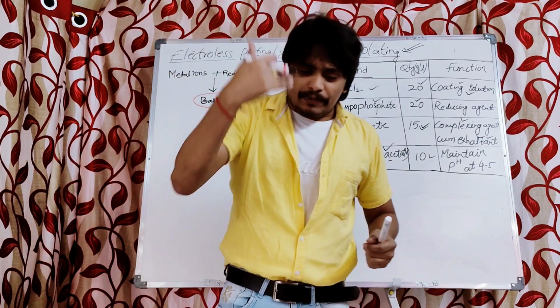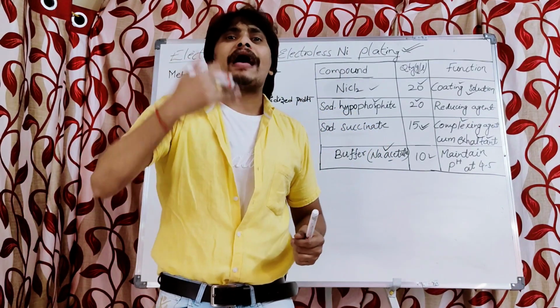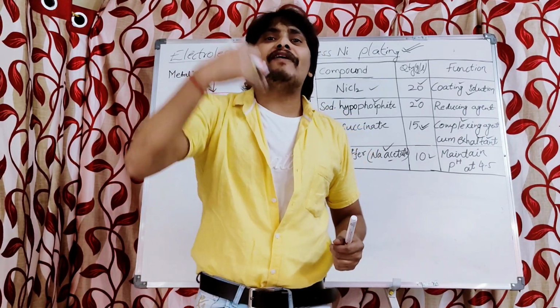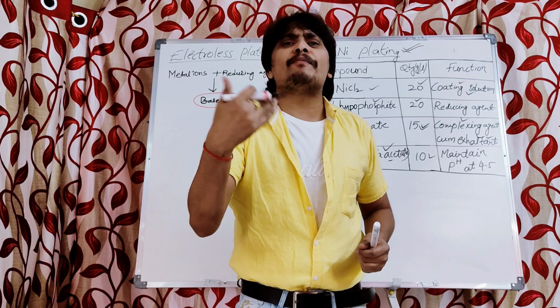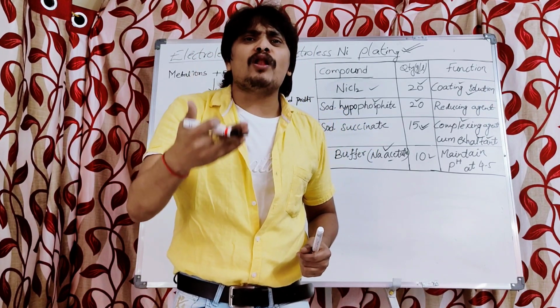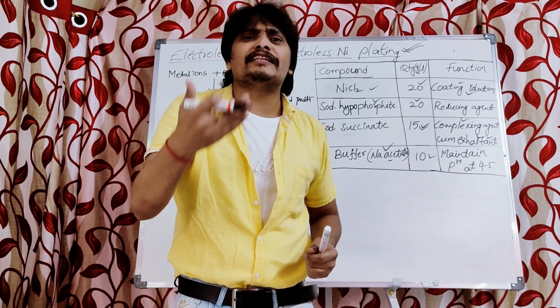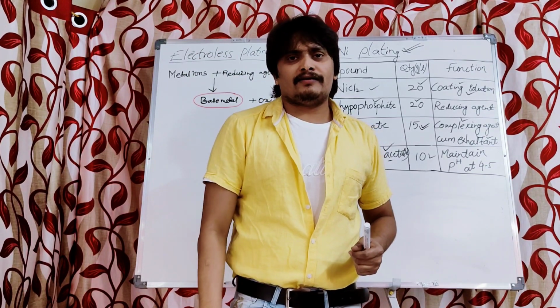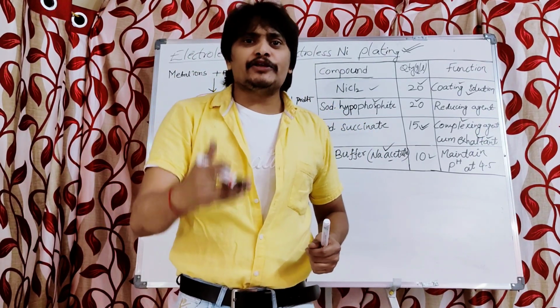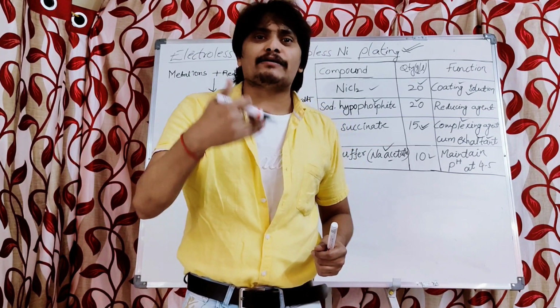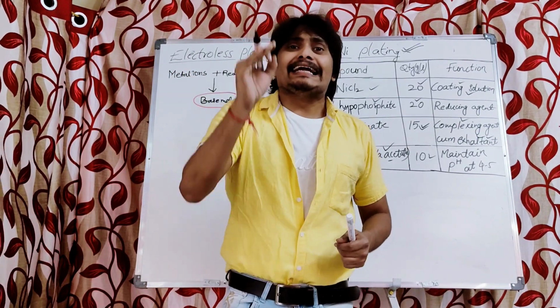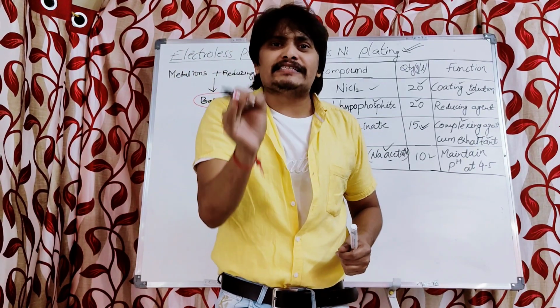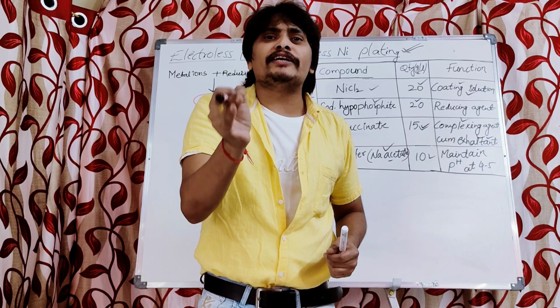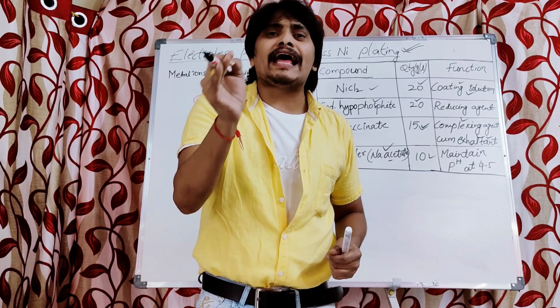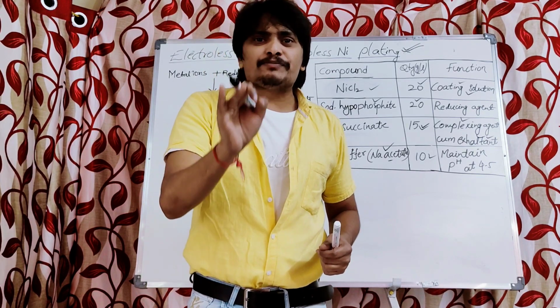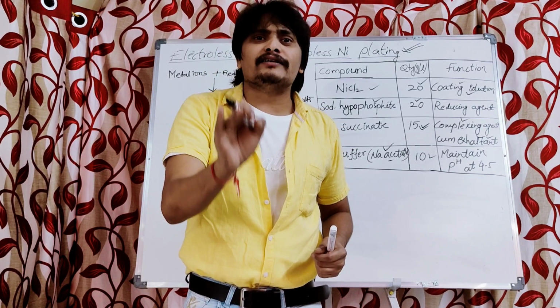Right. So after preparing the bath, what we need to do is we have to activate the base metal. Now, what do you mean by activation of the base metal? Activation is nothing but the removal of impurities from the surface of the base metal. Right? So this can be done by using a suitable solvent or alkali, that is the base, followed by acid treatment. That is, degreasing of the base metal is done by either a suitable solvent or alkali, followed by acid treatment.